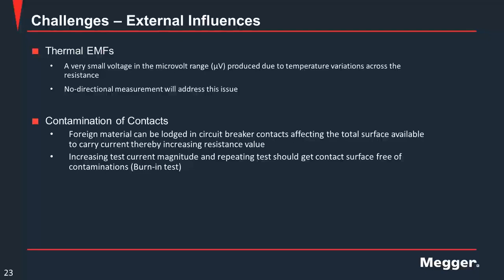The next is the contamination of the contact. As an example, on the CB foreign material can be lodged in the contact, and this will affect the total surface available to conduct electricity. Because the surface is lower, the resistance value will be increased. So increasing test current magnitude and repeating the test should get the contact surface free of contamination. So the contamination of the contact also can have an effect. We have the challenge of how to eliminate this.